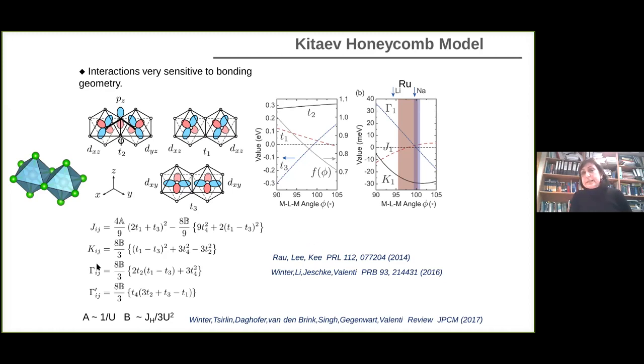So let me show you in this slide why it's so important if we introduce a strain in this material. And what I'm showing is basically perturbation theory calculations of the magnetic interactions. So when you apply perturbation theory on the Hubbard model, where t are the hopping matrix elements. So here I'm showing the important hopping matrix elements in ruthenium trichloride. So basically the nearest neighbor type of hybridizations that one can think of. This is ruthenium, ruthenium and chlorine. So I basically define three basic ones. This is interaction through the chlorine, while these are direct d-d interactions.